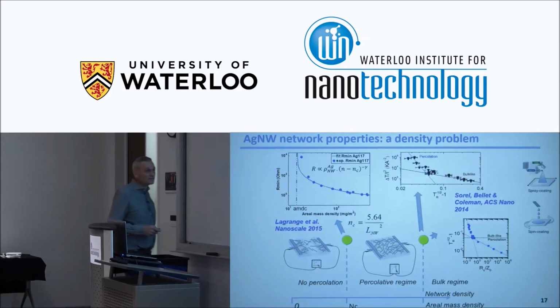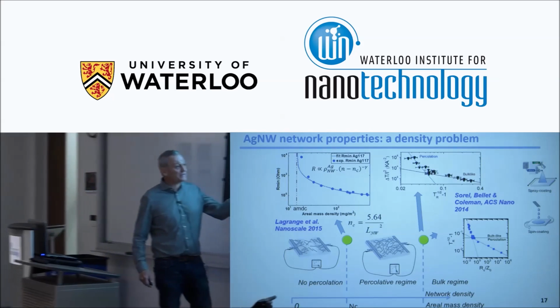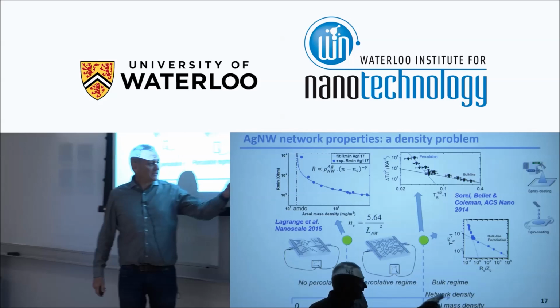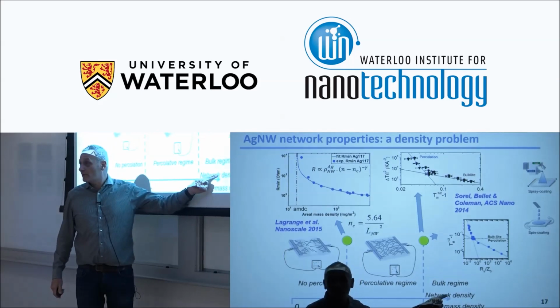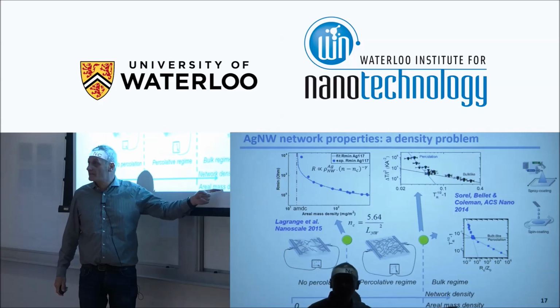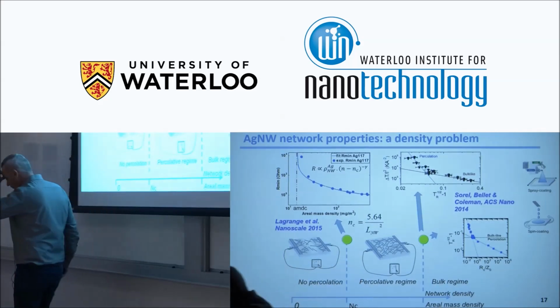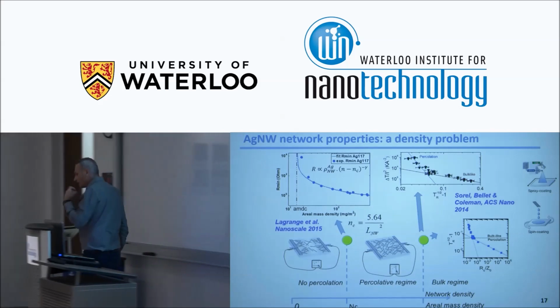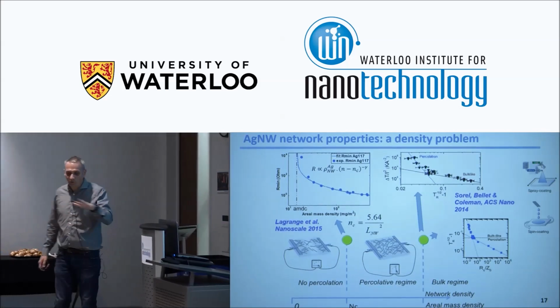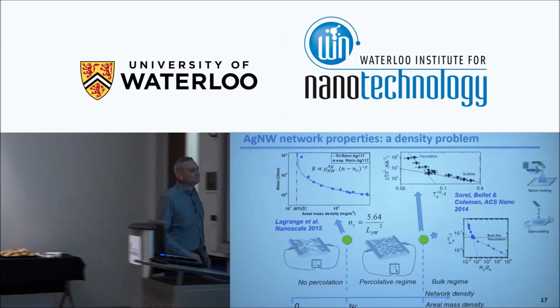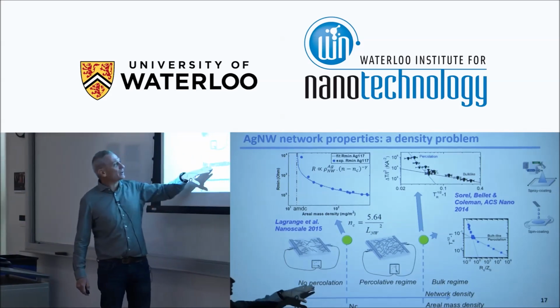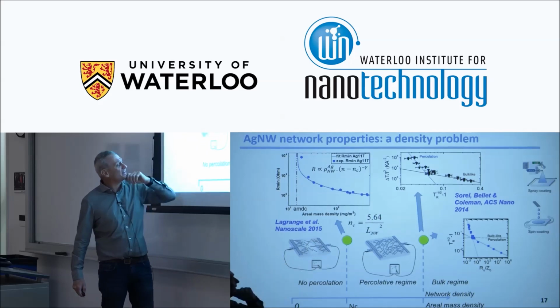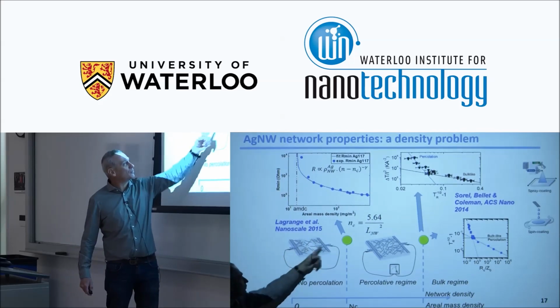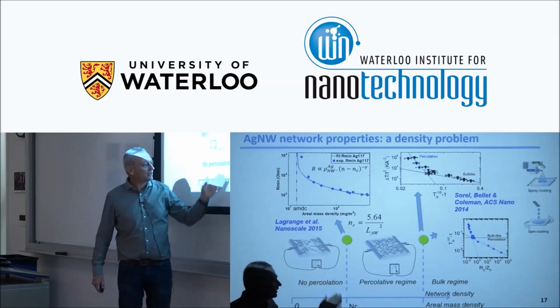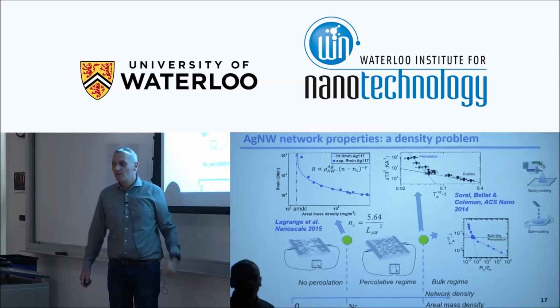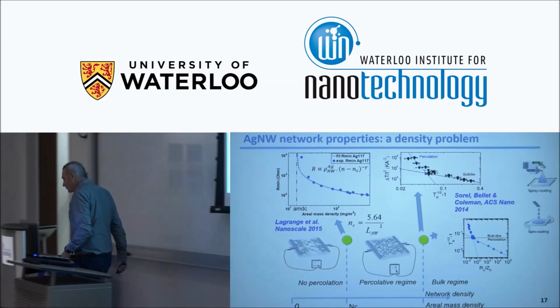And for physics, this is a kind of a density problem. If we put an axis here, this is network density. This is counted as the number of nanowires we put per surface area, or what we prefer is the areal mass density. This is the amount of silver, for silver nanowires, in terms of milligram per square meter, we have put on a substrate per unit area. And below a critical point, there is no percolation. That means between the two electrodes at opposite sides, there is no path for an electron to go from one side to another side. Then suddenly we reach a kind of a critical density, and above this, we have a percolative regime. And that's what we call stick percolation.